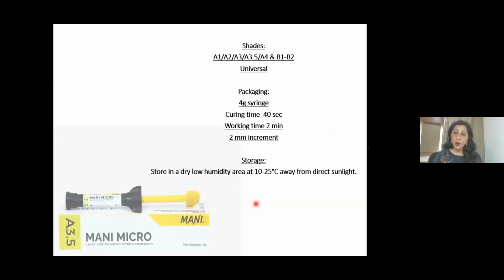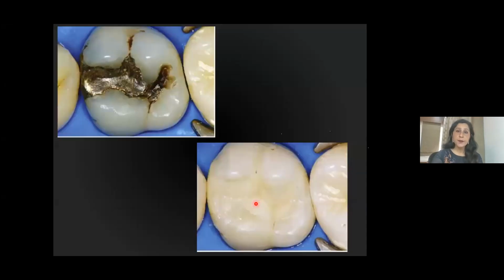Mani Micro, cure it for 40 seconds, and the working time that you get to work with this material is 2 minutes. If you are going to use it for more than 2 minutes, if your placement is such that your restoration is too big and you feel that it's a complex restoration, then always remember to put off your light in other direction so that it may not interfere with the setting reaction. So this is a result that you can get with microhybrids.